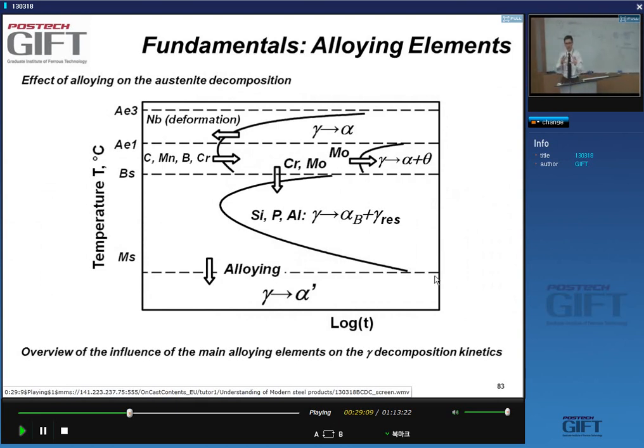Okay, so remember that. We'll talk about this in the course a few more times because, as I said, some plate products, some high-strength sheet products make extensive use of this method to refine the microstructure. And it's very widely used in steel products. By the way, I also want to say that the amounts of niobium that you have to add are very, very small. Typical amounts of niobium are 0.04 mass percent or weight percent of niobium. Around that, this is not the absolute value for all grades, but that's the kind of typical value.